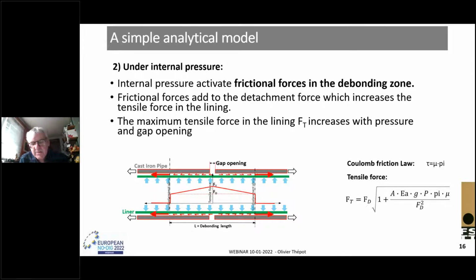It is also possible to calculate the gap opening that causes the liner to break. The breaking force of the liner must be greater than the debonding force, as in the case of zero pressure, but with a greater margin to take into account the effect of the frictional forces activated by internal pressure. Notice that in the presence of internal pressure, the tendency for lining debonding is lower.